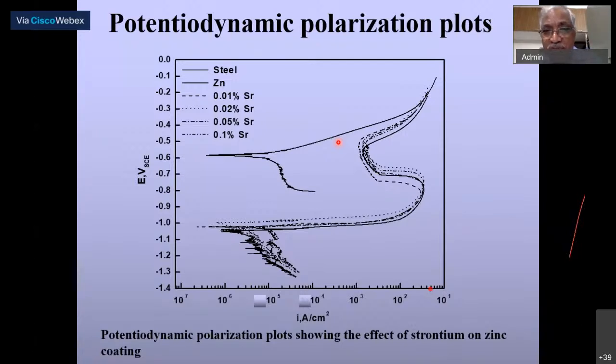That's why if you do polarization curves at different scan rates, you see that the passive current density is decreasing. Of course, corrosion is also a time-dependent process. You know, it takes time to build the passive layer and all. But apart from that, you have these problems.